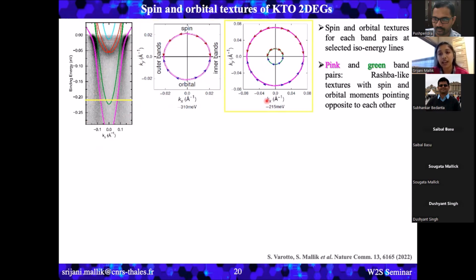It shows similar Rashba-like texture. And the alpha R was calculated to be 10 millielectron volt angstrom for these two band pair. Now, of course, we want to know more about this band pair, because here we see the large Rashba splitting.